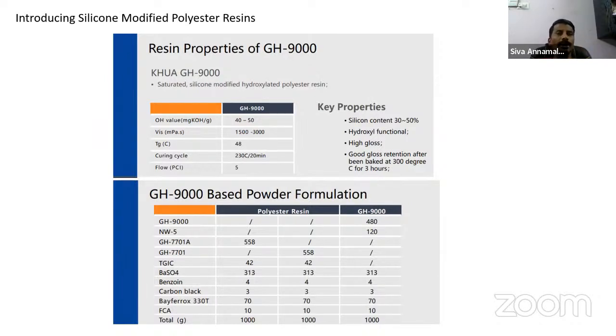But some people do 600 degree exposure for only a few minutes, 5 minutes, 10 minutes, and then they suddenly quench it. What is more important is that even if you expose at 300 degree or 400 degree, the temperature is not very important. Longer exposure is very important.